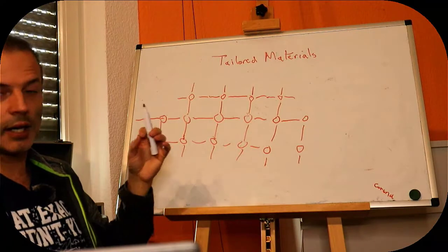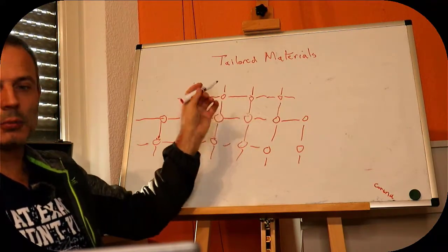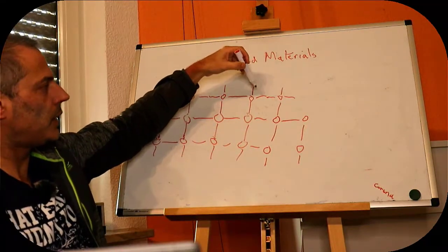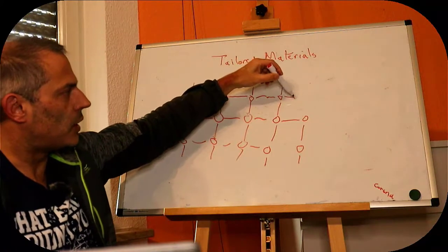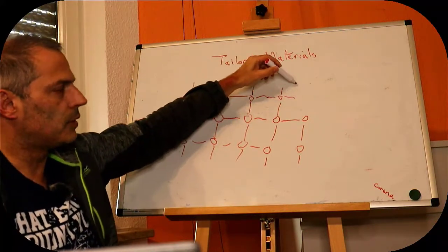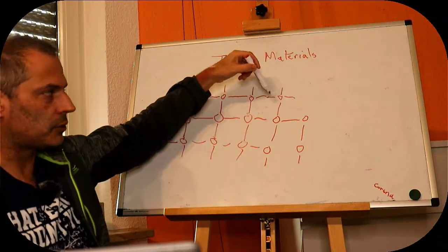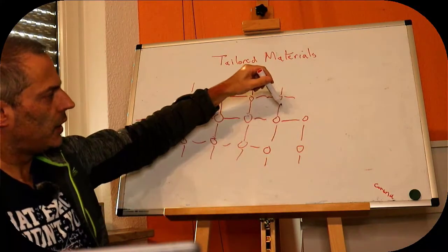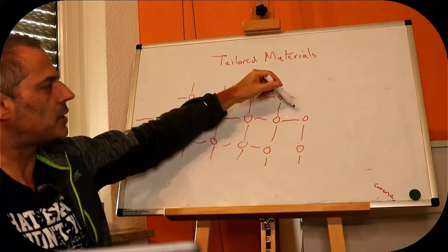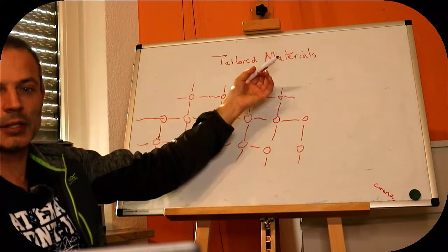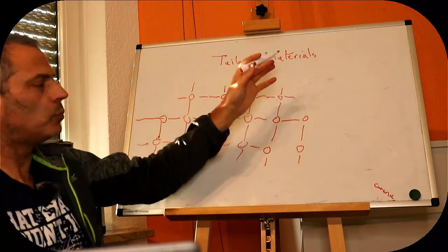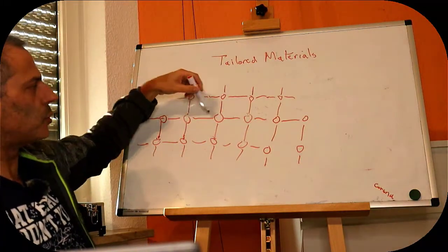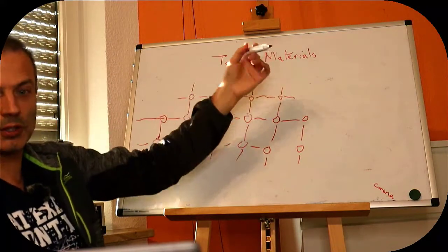But what I'm interested in at the moment is these different sites, because that is where catalysis will happen. If we have a molecule that comes along, it will either react preferentially with the really reactive sites on the outside corners, because those are the ones that have more bond energy, or it will snuggle down on the inside corners because then it can interact with more atoms. It depends on the species that we're going to interact, but what it very seldom does is glom onto the surface, which is flat. It is much more likely to interact with these interesting sites.